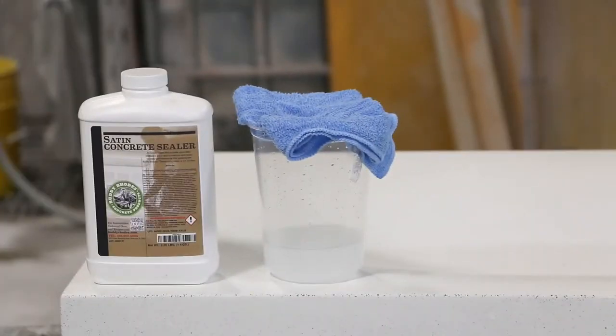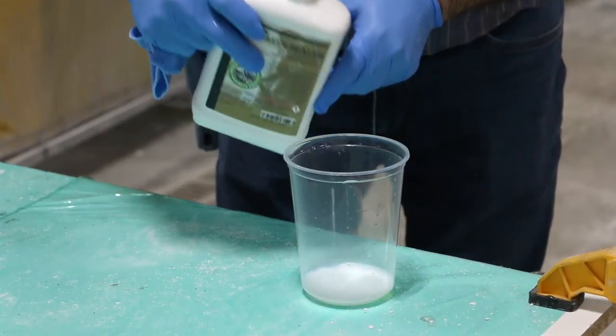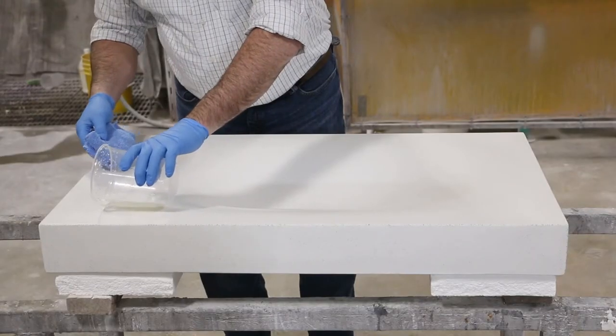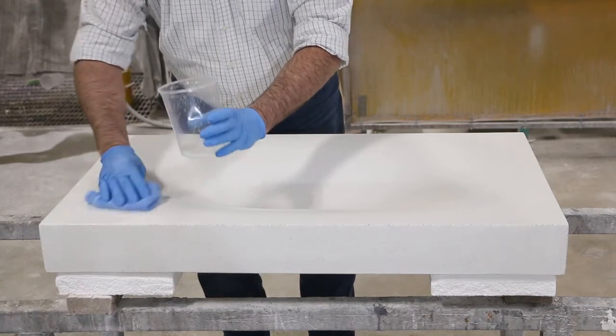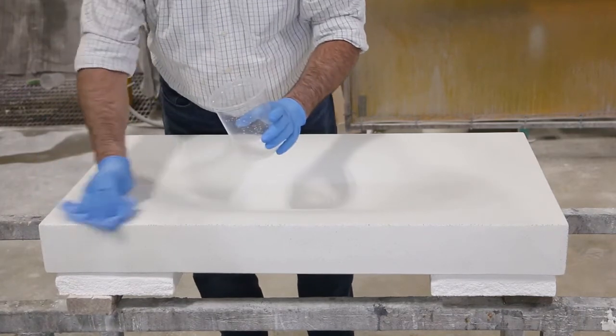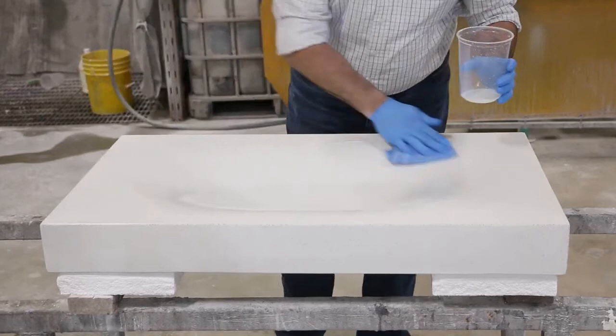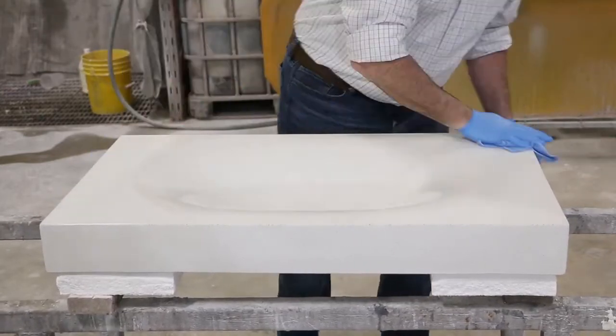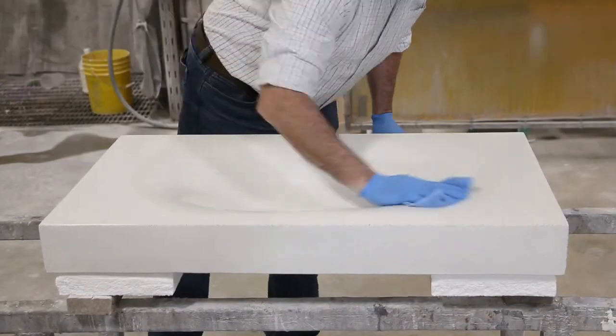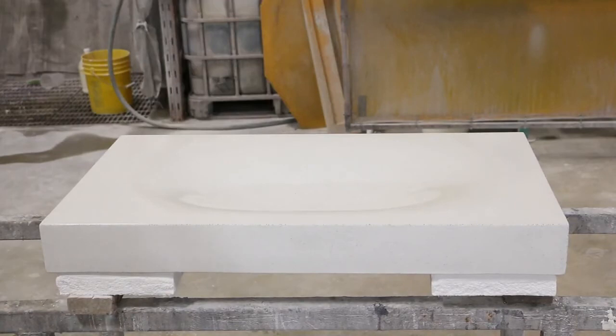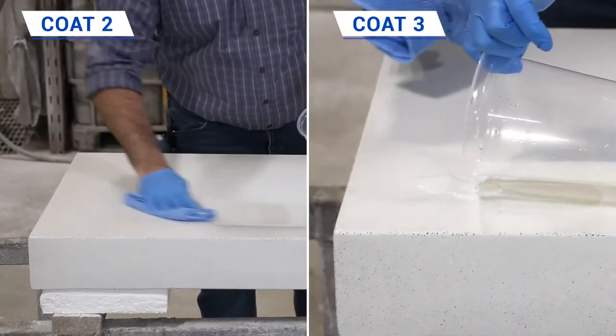I then apply Buddy Rhodes Satin Sealer to the surface and wipe a thin layer over the entire surface, overlapping to avoid streaking and over-application. A little goes a long way. Keep the coats thin. Allow to dry and follow with at least 3 applications for a bathroom vanity.